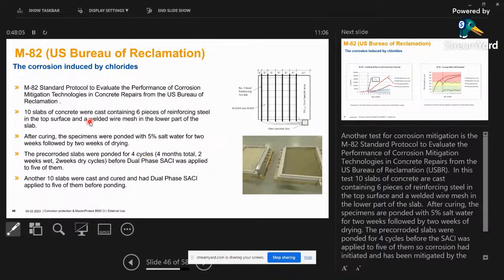This was a bigger scale test where a few specimens of small slabs were cast. They were all ponded with a 5% salt solution. Now, even sea water will have 3 to 3.5% of salt, NaCl. This is 5% salt water, so severely loaded with chlorides. And it ran for 4 months total, with 2 weeks wet, 2 weeks dry cycles.